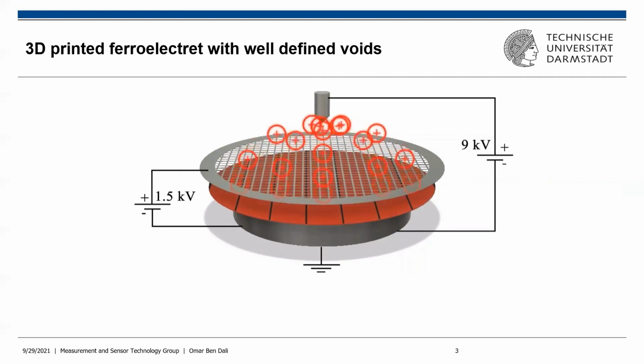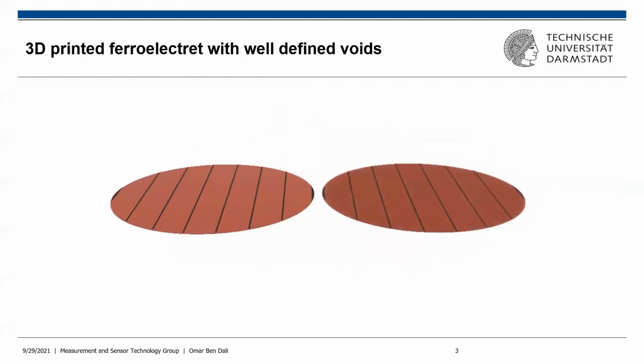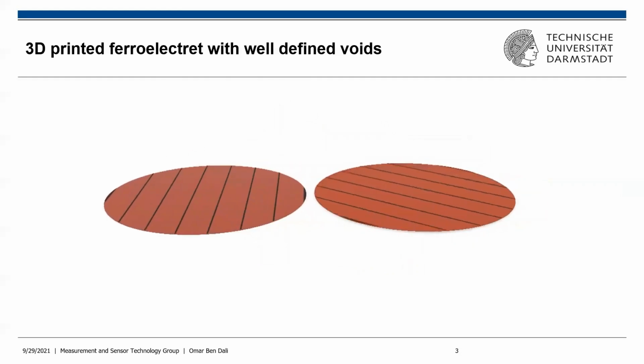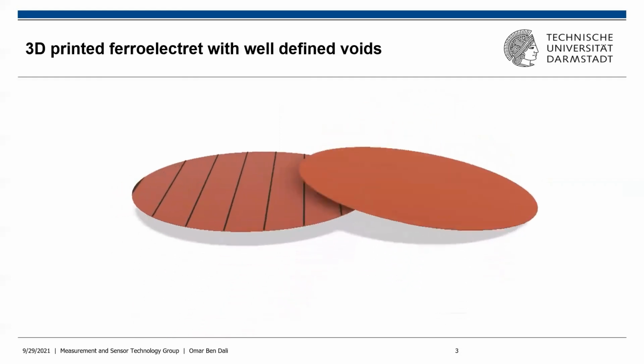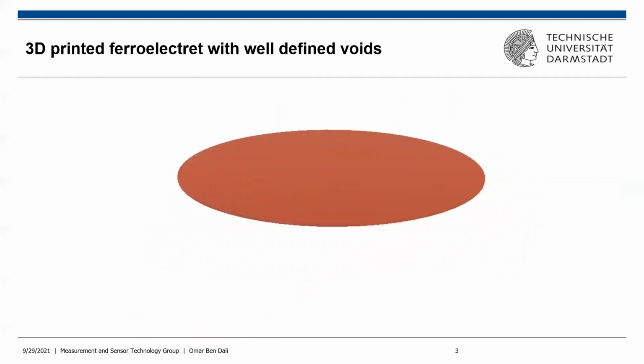So we get two parts which are charged with opposite polarization, which can be considered as electrets charged with different polarities. Afterwards, the two charged parts are glued together such that the ridges in the two parts are at 90-degree angles to form an artificial ferroelectret.